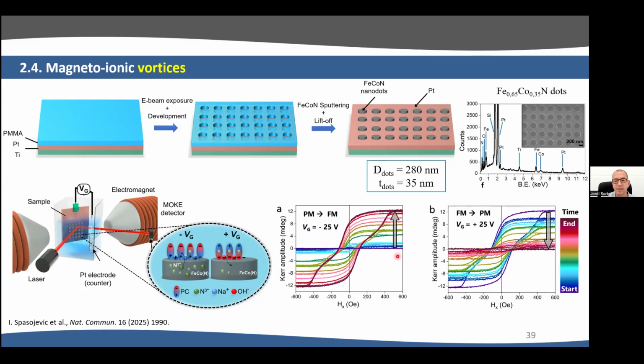So this arrow here means increase of time, and this arrow here is the same, applying minus 25 volt and 25 volt positive. So starting from the paramagnetic state iron cobalt nitride, you can see that when we increase the time, there is first the creation of a square hysteresis loop that is typical of coherent rotation. And then as we increase further the time, we could see with Irena, actually the first co-author of the paper, that the loops get constricted and we increase the magnetization progressively. And then if we change the polarity, we start with this constricted loop, we go back to square loop, and finally paramagnetic. So the effect is fully reversible.